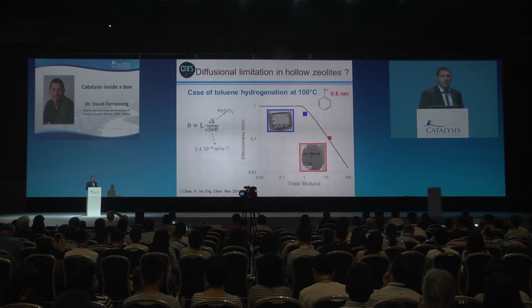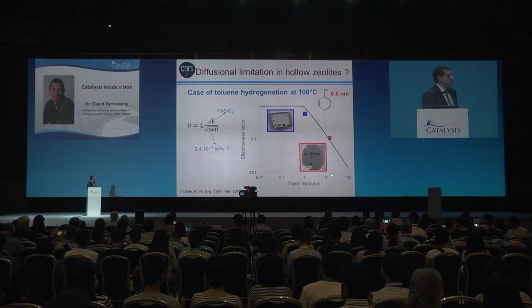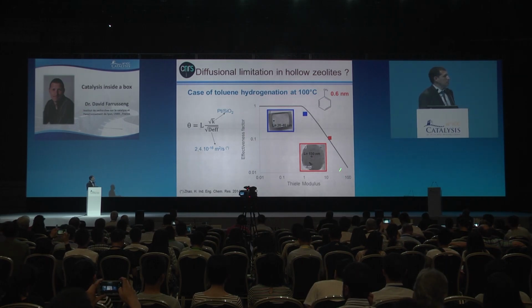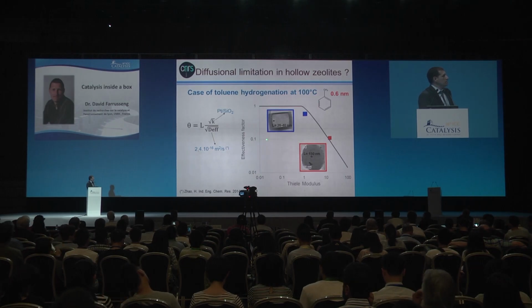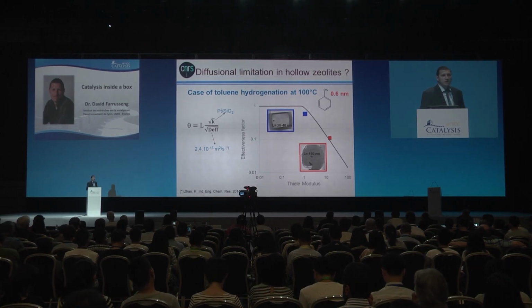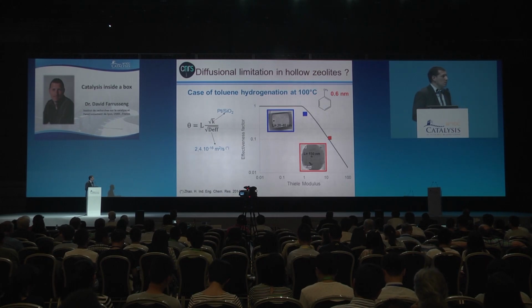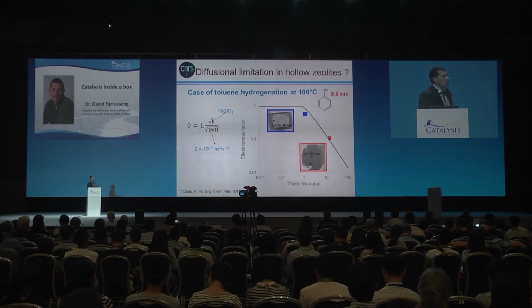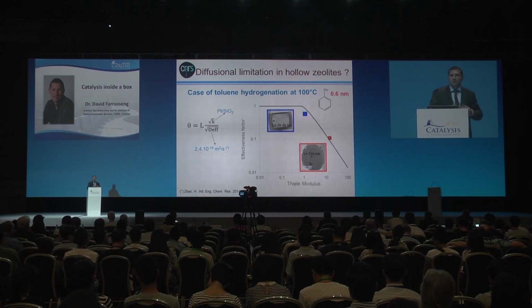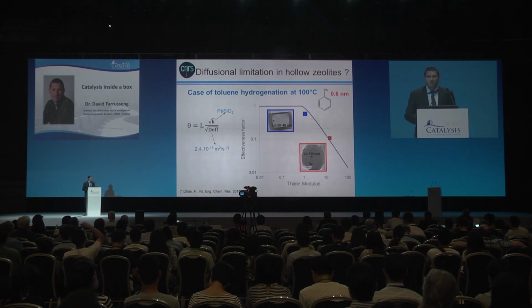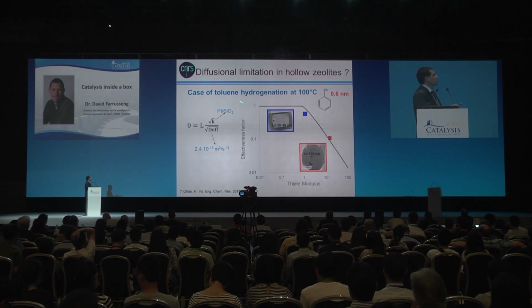Briefly, if you have a Thiele modulus larger than 1, you will be limited by the diffusion. For example, if you have 10, you have an effectiveness factor of about 0.1, meaning that only 10% of your nanoparticles will be active, will work under reaction conditions. Instead, if you are below 1, all the particles will work. So how can we estimate that? The expression is here.